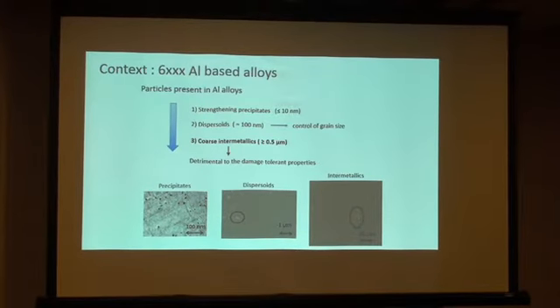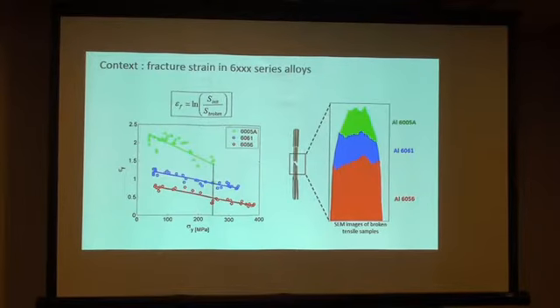So today I will talk a lot about particles, and when I say particles, I am always talking about these big particles which are bad for the damage properties. So the beginning of this study was that we performed tensile tests on three different aluminium alloys, namely 6056, 6061, and 6005A. And what you see is that those three alloys have relatively similar chemical compositions.